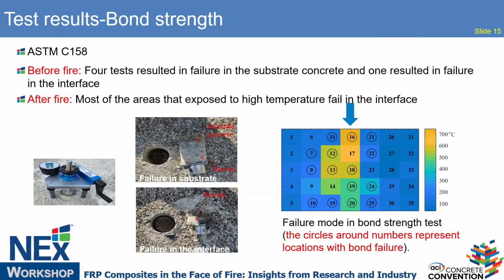And those are the results for the bond strength test. Before the fire, we did five tests, and four of them failed in the concrete substrate, which means the slab, the overlay, and the concrete have a relatively good bond strength between the concrete substrate and the overlay. After the fire, we tested the bond strength over the whole slab, especially in those areas which were exposed to the high temperature, and we found that the majority of them failed in the interface.